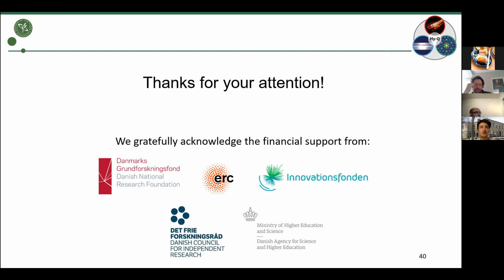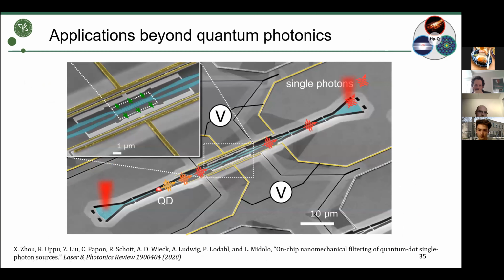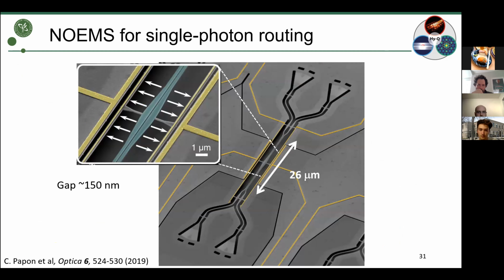It's a good question, thanks. Generally, we say that this is not the case, because the fields, let me see if I can go back. Here, I would say the electrostatic field is mostly localized within these two gaps, so far away from the optical region where the waveguides are. We probably estimate that some stray capacitance, some stray fields can still be in the proximity of the gallium arsenide. That per se is not a big problem.